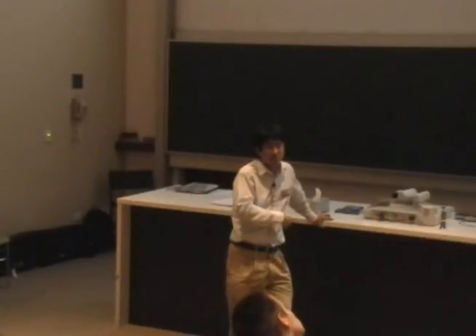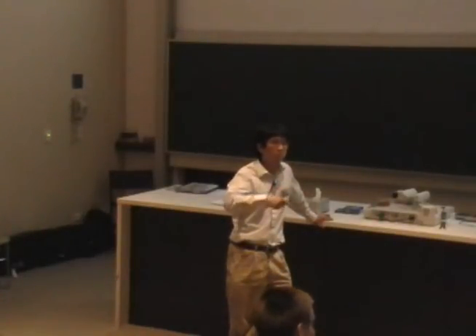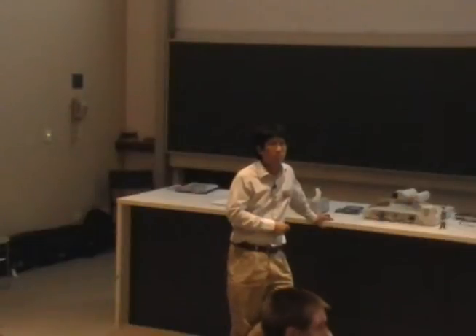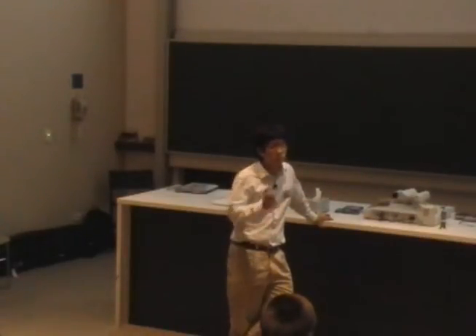So, in the paper from the UCLA group, they did that experiment. They washed their P3HT in DCM and then used that P3HT to spin coat the P3HT film. And they demonstrated that washing or not washing made very little difference in terms of device performance. Obviously, I've dropped DCM onto the P3HT layer and it doesn't wash away. It stays as it is. So I'm fairly happy that it doesn't dissolve away in the DCM.